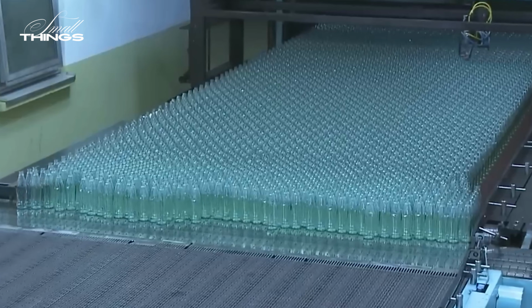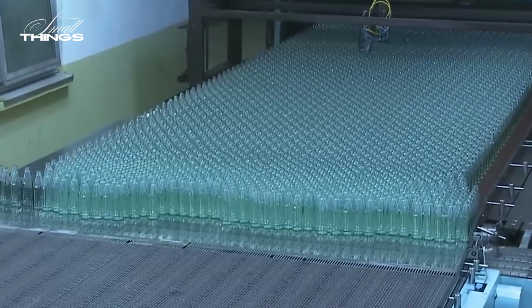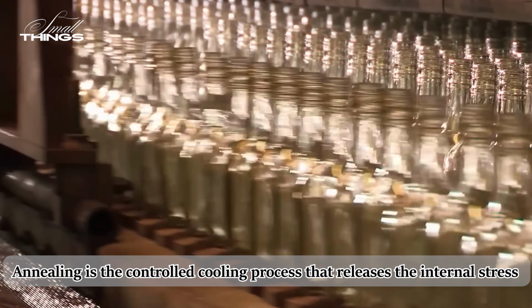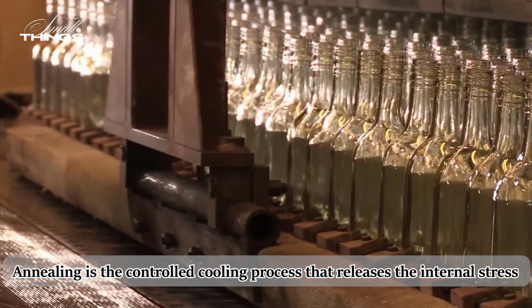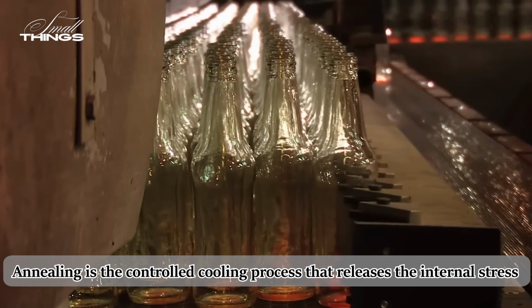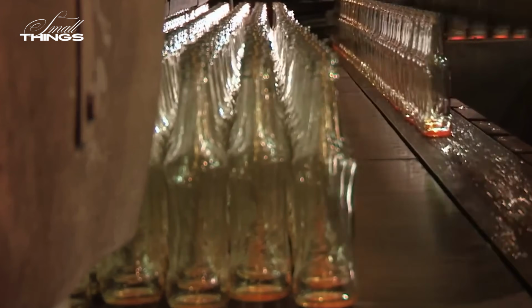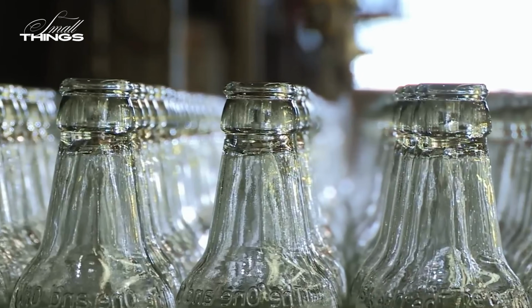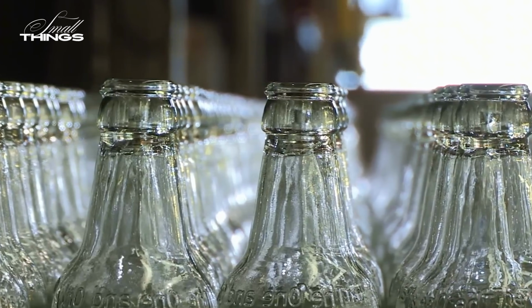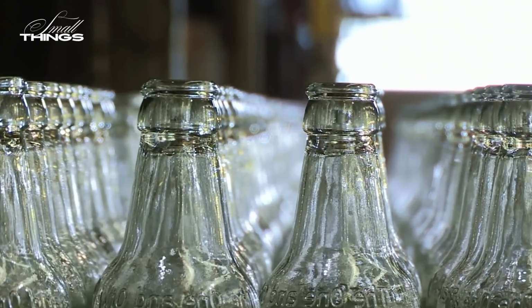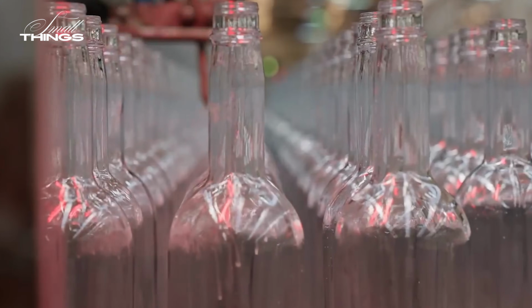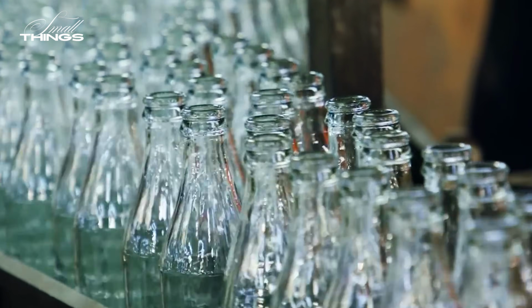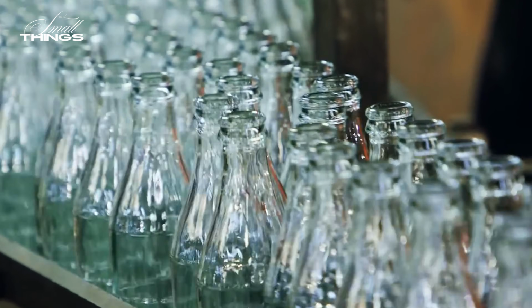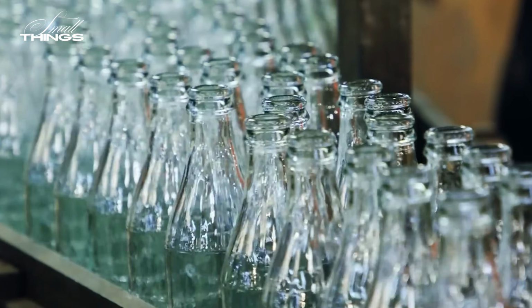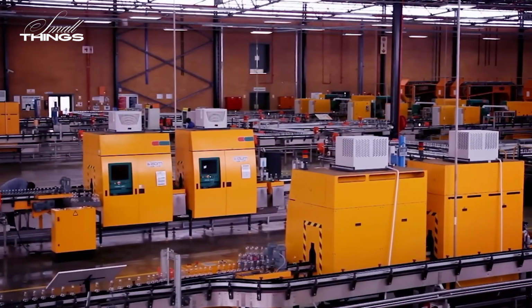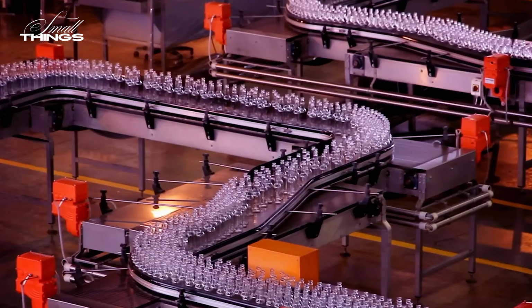After shaping, bottles travel through a long annealing oven. Annealing is the controlled cooling process that releases the internal stress that builds as hot glass contracts. Glass cooled too quickly develops tension between the faster cooling surface and the slower cooling interior. That tension makes the bottle fragile and unpredictable. Annealing brings temperature down gradually until internal stresses equalize.